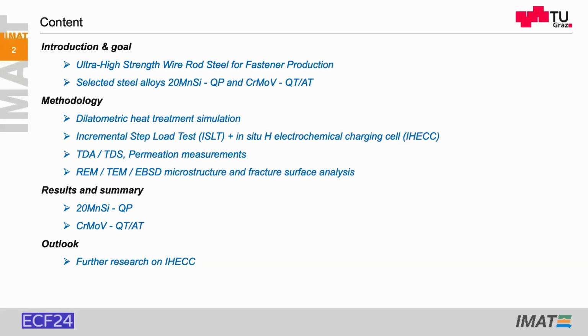What are ultra high strength steels, rod steels for fasteners? That is my introduction. We selected two types of steels for producing ultra high strength screws. It was 20 manganese silicon, quenched and partitioned, as well as chrome molybdenum vanadium, quenched and tempered or austempered. The methodology I will explain to you later on, then the results and our further research on our developed method.